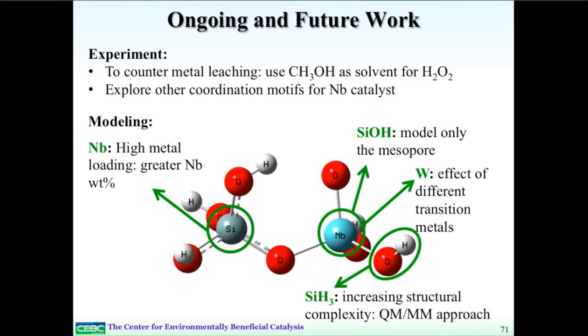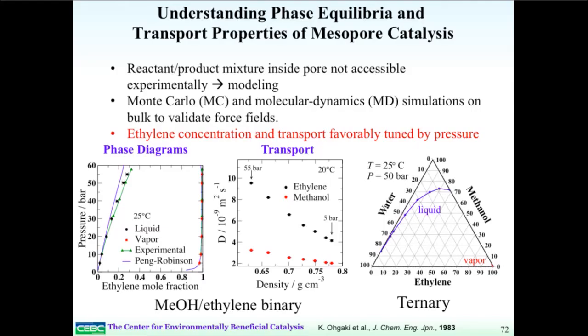One aspect that I've been involved in with my group is to try and look at the solvent media itself. So here, as an example, we have phase equilibrium that we've calculated using Monte Carlo simulation. This is for an ethylene methanol mixture. And we see here the gas phase is primarily ethylene. We can get up to a 30% mole fraction of ethylene in the liquid phase. These predictions have been experimentally done, and so our models are actually fitting the experiment very well, much better than standard Peng-Robinson modeling you get in